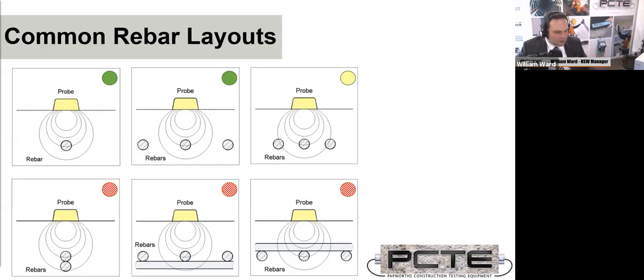The process, if you have inconsistently spaced bars, is going to be marking them up on the surface. So you can isolate individual bars with consistent spacings around them to get those critical cover depth measurements. If the goal is what's our lowest cover, you want to be able to measure at various places over your survey element an isolated bar closest to the surface, because that's going to be the accurate measurement.